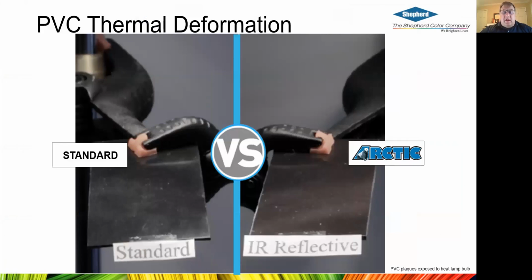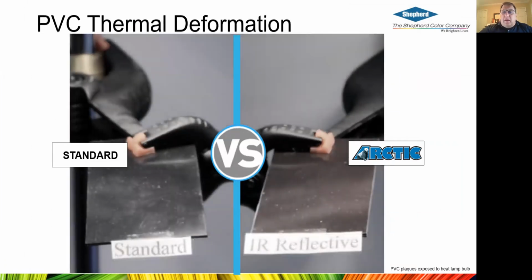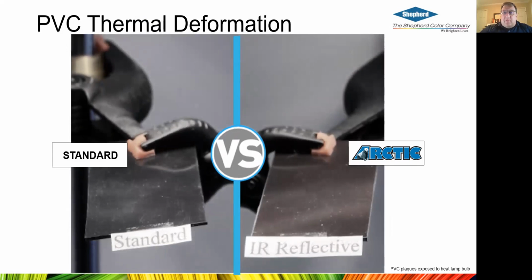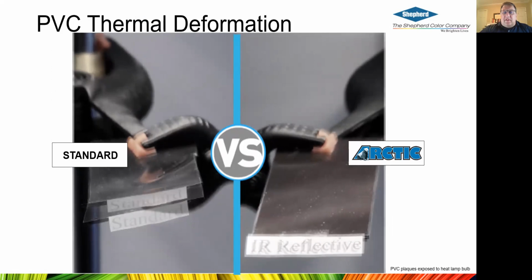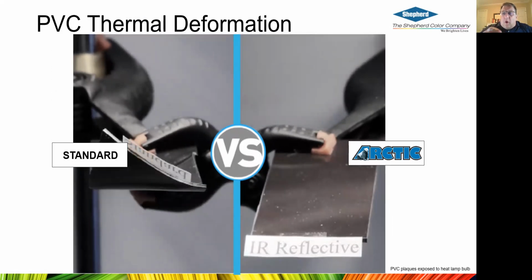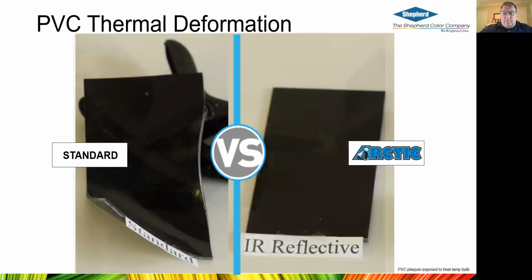One of them is PVC siding. So this is in a lab setting. We have two PVC plaques of the same thickness, one pigmented with standard black pigments and the other pigmented with IR reflective pigments. What we did then is we put on a simulation of the sun, a heat lamp bulb, and over a few minutes, as these pigmented plaques absorb the light coming off of the bulb, you can see that the standard pigmented chip starts to warp, and that's because PVC will thermally deform if it's exposed to higher temperatures. So even though they're very similar in color, you can have a PVC plaque that is much more dimensionally stable using the Arctic IR reflective pigments.